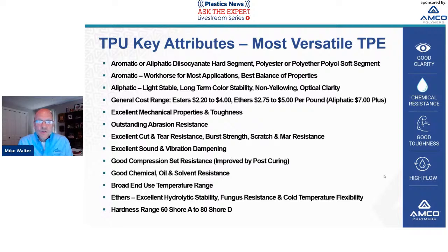TPUs have a broad end use temperature range, depending on which grade you're choosing. And one key note about outdoor applications: if you're using TPU in an outdoor application, the polyether is the way to go. They have excellent hydrolytic stability or resistance to moisture, excellent fungus resistance, and cold temperature flexibility. The hardness range for TPUs is 60 Shore A up to about 80 Shore D.